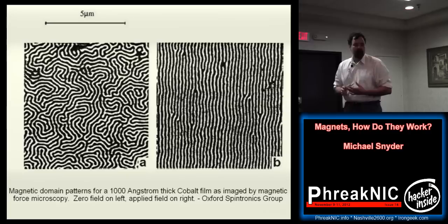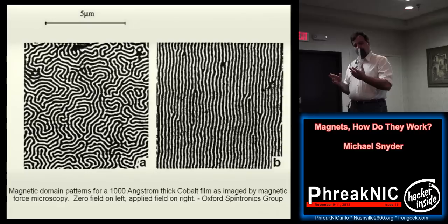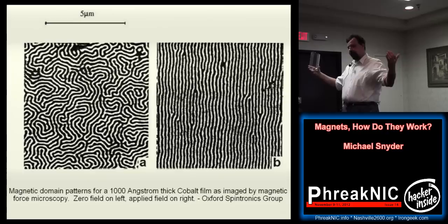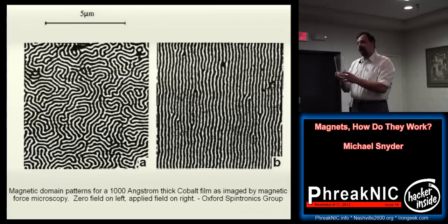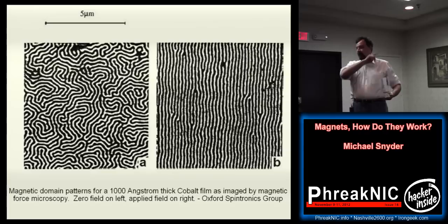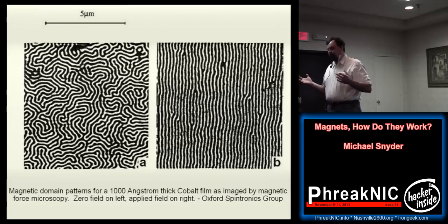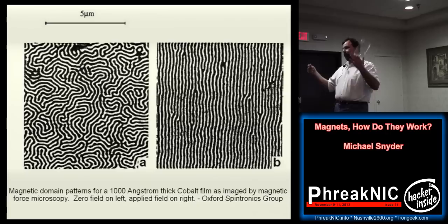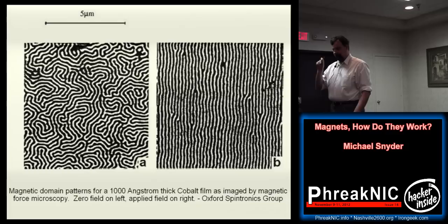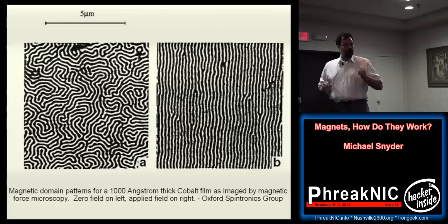Now how do I make a permanent magnet? Well, I would take a very strong magnetic field and apply it to this, and it would straighten itself out. It would align itself. And then I would pour epoxy in here and let the epoxy set, and that would be a permanent magnet. All permanent magnets are made this way. It's at a nano level, but it's the same thing. We align dipoles, neodymium magnets, for example. We heat the material, we let it cool below the Curie temperature, and it becomes a magnet until you reheat it or break it again, and you lose some domains. Alignment is what I'm trying to say.